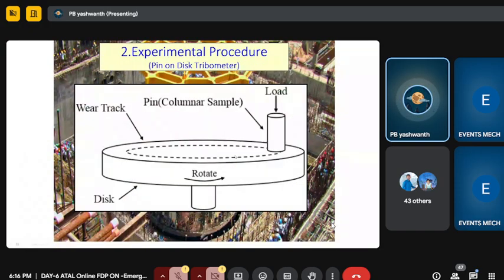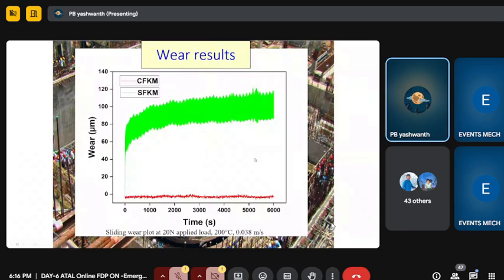This is the experimental setup we have for any kind of tribological pin on disc test. Though they can replace the pin with balls, in my condition I cut an extruded rubber pin and the disc was rotated. There is a transducer to calculate the wear encountered, a positional transducer to find the z direction, and one more frictional force sensor which senses the frictional force. Once you find the frictional force, we all know mu equals F by N. We know the normal force, obviously. Then we calculate the coefficient of friction. Then these are the wear results we get, comparatively placed.